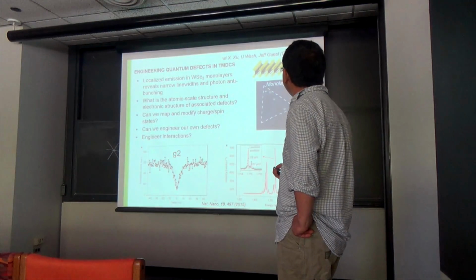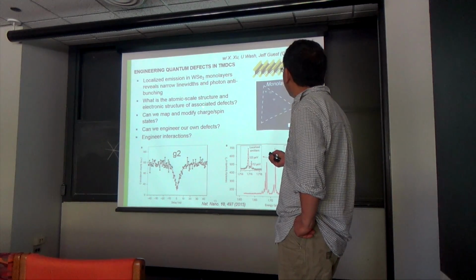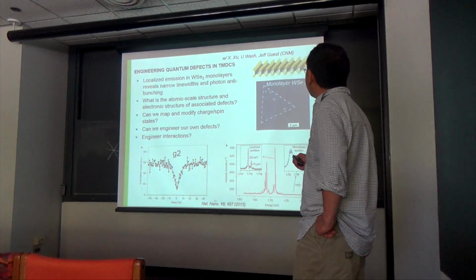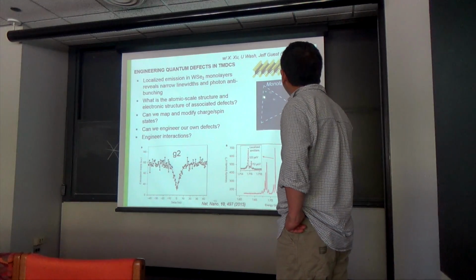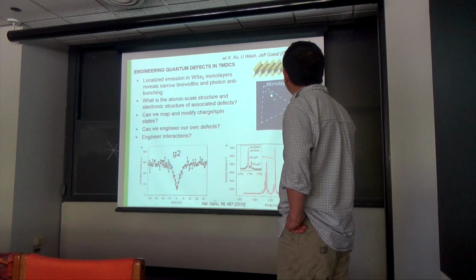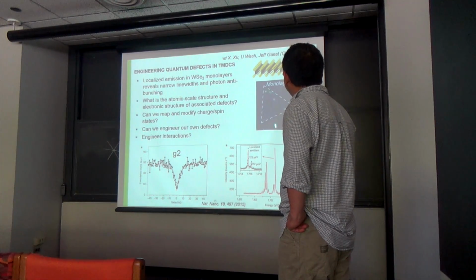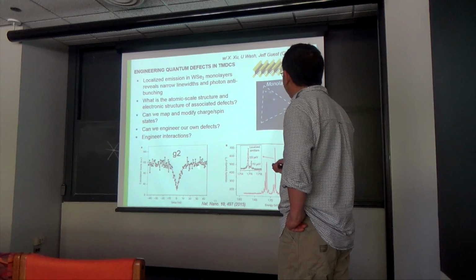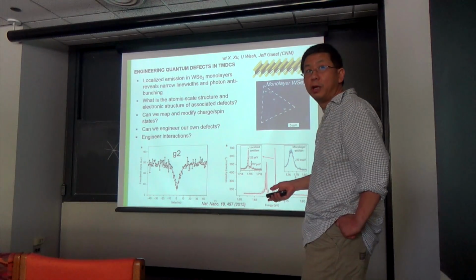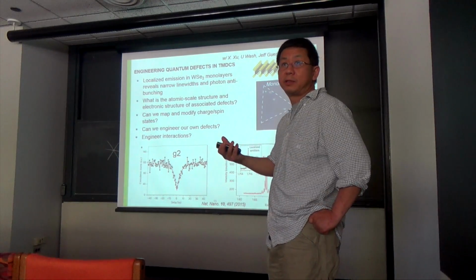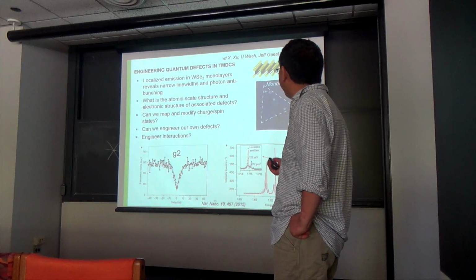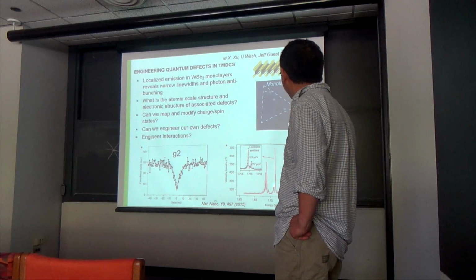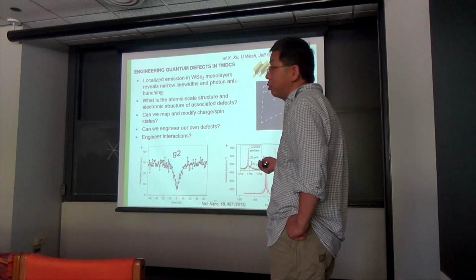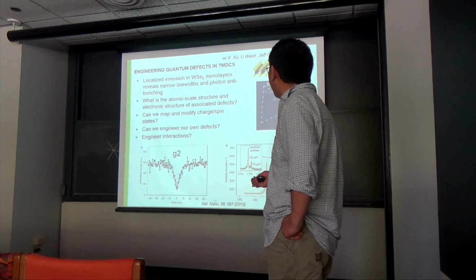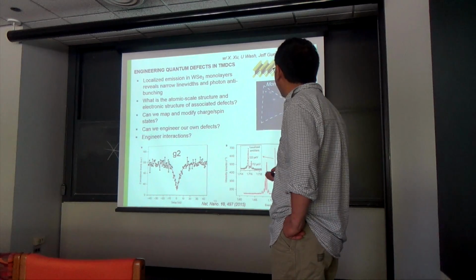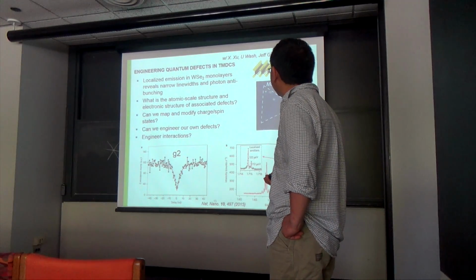What they have been doing recently is looking at, for instance, defects in a 2D material, such as tungsten diselenide monolayers, with a group at the University of Washington. What they found is that the excitations from these defect sites are extremely sharp. So the question is why these defects give you such extremely sharp optical signals. Also, can you actually engineer your own defects in these 2D materials? Can you understand the coupling between the defects and the electronic spin state in these systems?